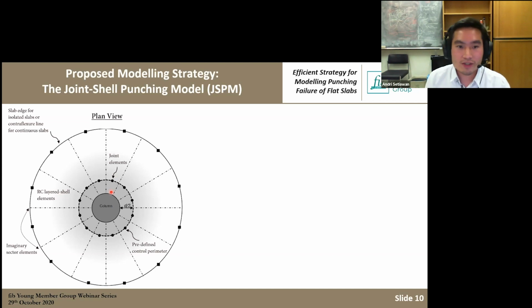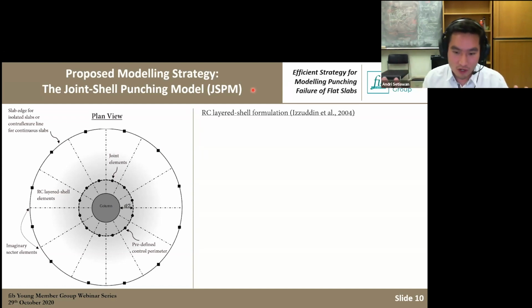So as you can see from the name, this is combining joint and shell. For the shell, you can typically use any shell formulation. It doesn't really matter which constitutive model or anything that you use, but the most important thing is that you need a model that is able to capture rotation accurately, because the critical shear crack theory assumes that the resistance is directly governed by the rotation. So the accuracy is dictated by how accurate your shell is in capturing the rotation.